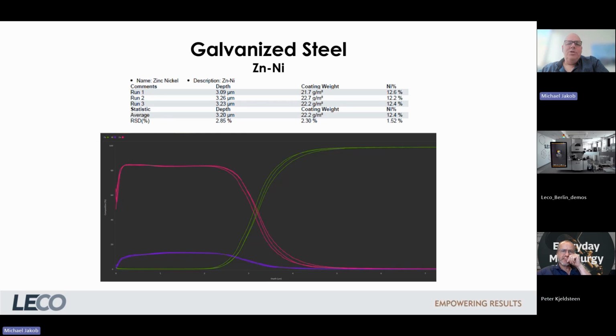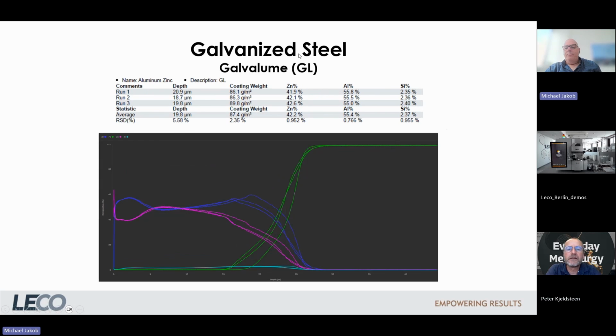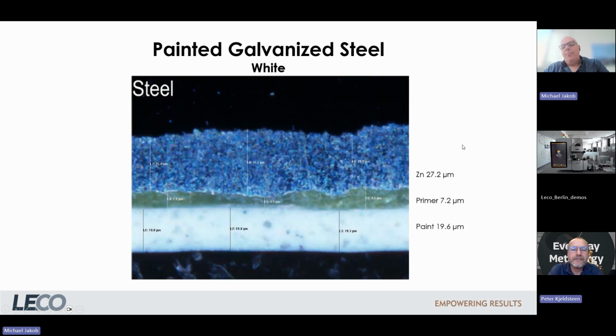So, if you take a very simple thing, galvanized steel, you see the green, that's the surface here on the left side. Then we go some 7-8 micrometers into the material, and you see a 3 point something micrometer layer of zinc, and then the steel comes, the iron goes up, and here you have your interface. That's for fun. I have hundreds of such things. Just one thing that happens is quite interesting.